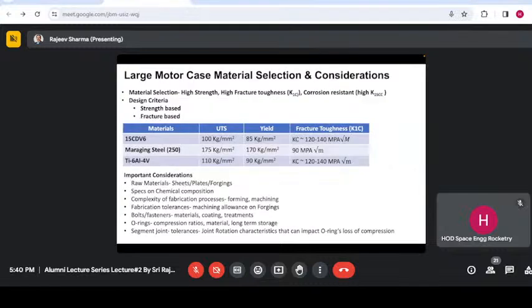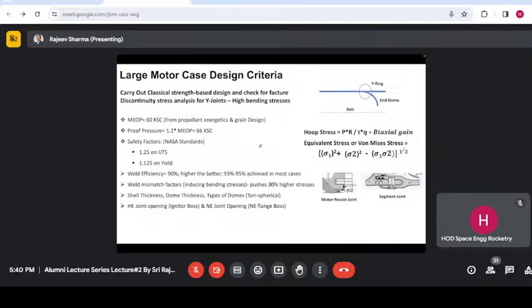And then, designing the system with all these pieces, came the time when the first rocket motor was ready and we decided to do the burst pressure test. Imagine the amount of oil we had to put in the system, even for pumping the oil, and putting on the strain gauges. There were more than 100 locations for strain gauging on the dome, on the cylindrical shell, on the weldment area between the forgings and the sheets, and certain critical areas of the longitudinal weld seams. And the number of weldments was mind-blowing.